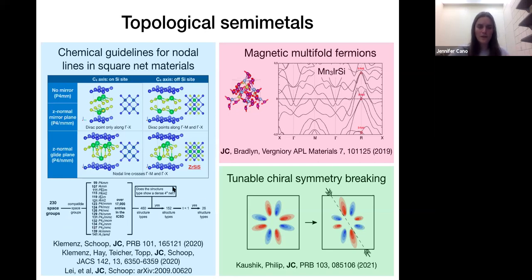So we filtered through all these materials in the ICSD, identified some structure types with that appropriate tolerance factor. And then we were able to find some other materials that can give us either Dirac cones or line nodes in these 2D square nets. So I think that case by case, there can be more steps, like a symmetry analysis to show you what is the ideal crystal structure that we would want, or the ideal tight binding model. And then maybe some kind of geometric factor that would tell you, if you have atoms with this crystal structure, what are the spacings that we need that would likely make the ideal tight binding model applicable. But we don't have a general principle for that.